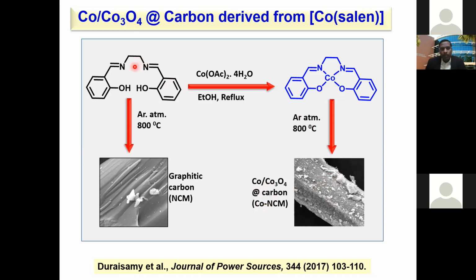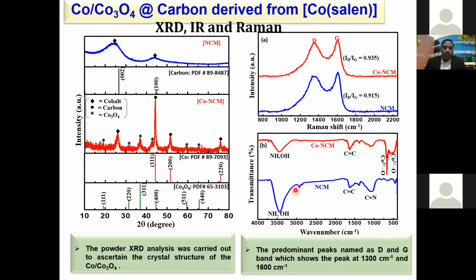For comparison, we have also decomposed the pristine ligand under similar conditions. You get only carbon here. In this case, cobalt and cobalt oxide. And then you characterize them, whether it has cobalt or cobalt oxide and carbon. You can see from the X-ray diffraction pattern that we have confirmation for the presence of cobalt oxide and carbon. And it can be substantiated using Raman spectroscopy and infrared spectroscopy, where the presence of carbon can be confirmed.